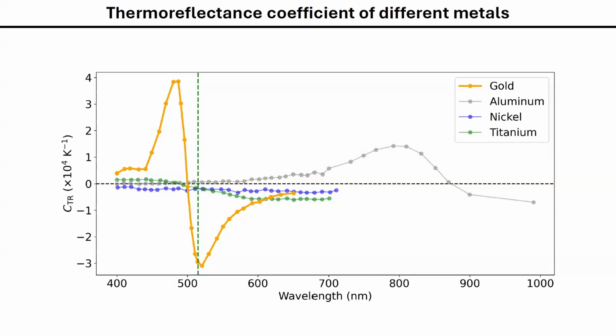But in our laser, we have wavelengths of 1030 and 515, which we use as pump or probe. First, we started using aluminum and using 1030 as our probe wavelength. It's the obvious choice. Also, the pump would be 515, it would have higher energy, so it all makes sense. But we were having significant difficulties in finding where the layers are, how we can measure different layers. We would need to prepare so many samples if we wanted to cover all this thickness range. So eventually, we decided to switch to gold. Gold has these two peaks of thermoreflectance where you can get a much higher signal using green or blue wavelengths.